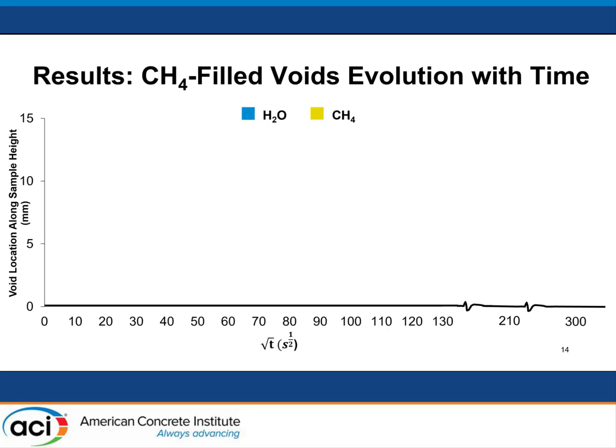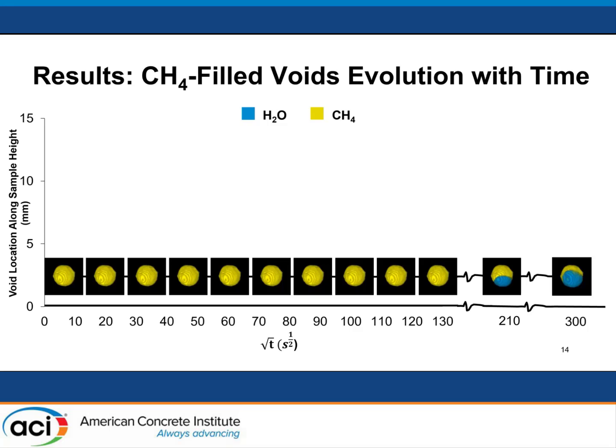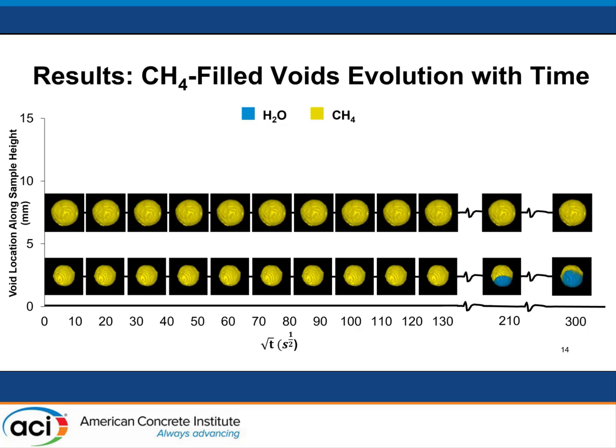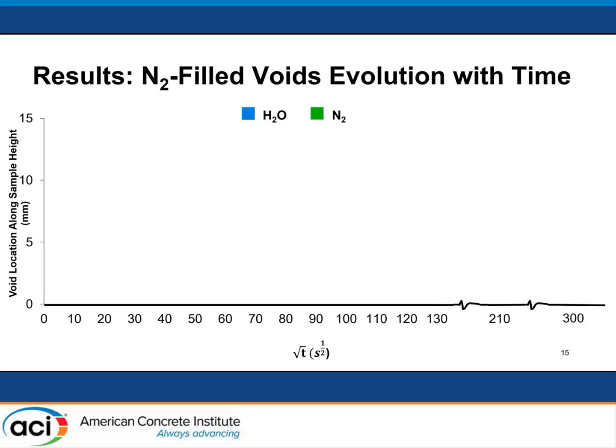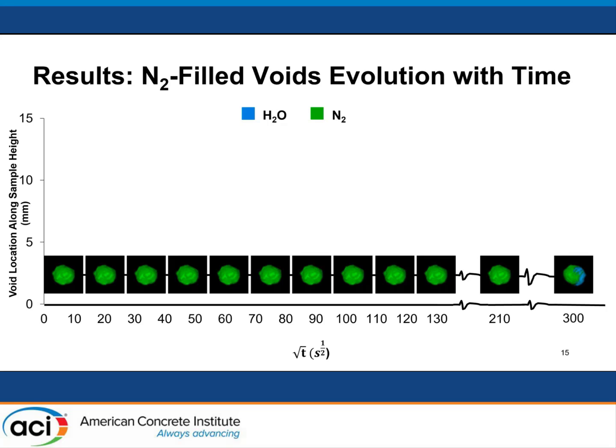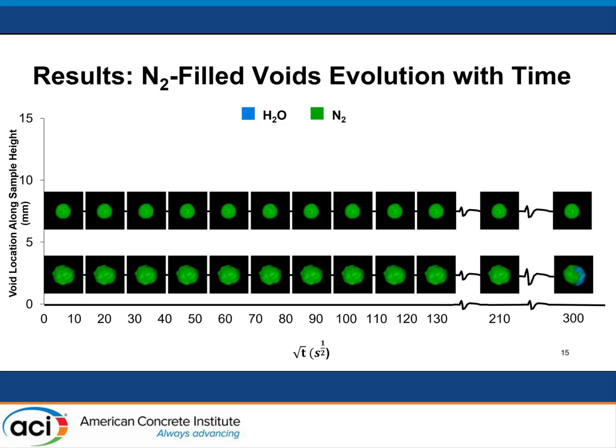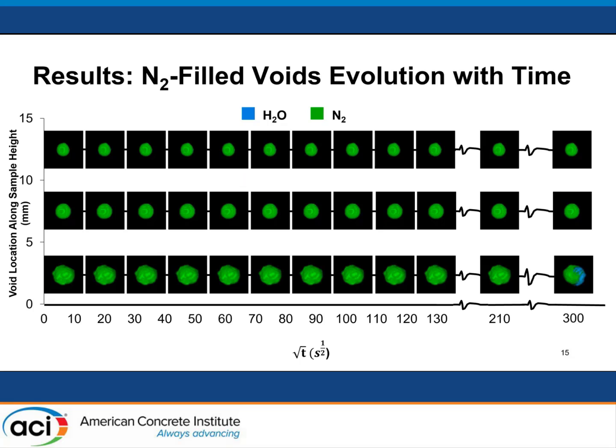And so I completed this with the methane filled voids as well. So one close to the bottom, which again didn't show any changes until about 12 hours. And then farther up on the sample, there really was no change observed, and even farther up, no change. And then for the nitrogen filled void, again, not much was seen over that 24-hour observation period. And that's going to be discussed more in later slides. And that was the same as you move up on the height of that sample.